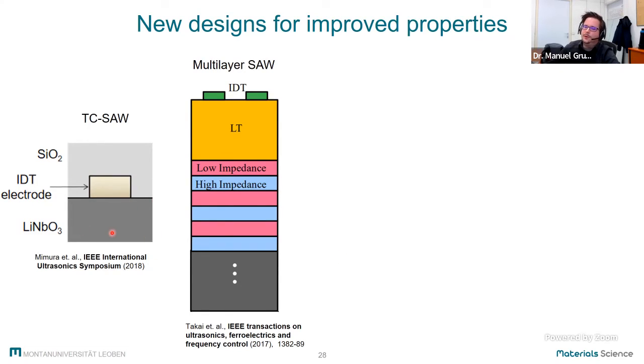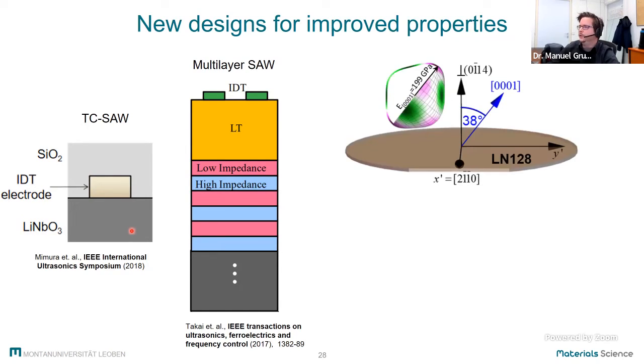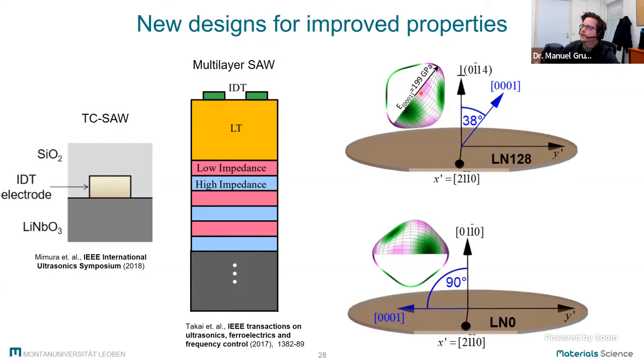And also this kind of configuration now enables different orientations of the wafers. This is what I would like to start with in the beginning. So up to now, we have only seen strength values for this configuration. We know that especially this wave orientation has a relatively soft surface. So one idea was to turn the highest Young's modulus in plane, and we tried so to increase the hardness and decrease the surface damage of our materials.